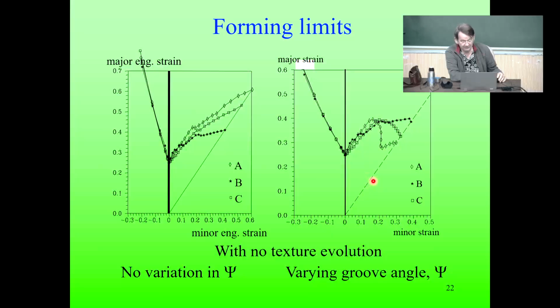Now, if we vary the groove angle, it has to be varied because we have to find the minimum strain in formability. Smaller strain at which there is already instability, you know, it doesn't permit to develop other strain mode. So here you see big changes happening for A, B, C textures. Now the B texture has the best formability, and for A and C, where we have the cube component, it went down. But here there is no texture evolution, only we varied the groove angle. We have to do both, so we have to update the texture evolution, and then also vary the groove angle.